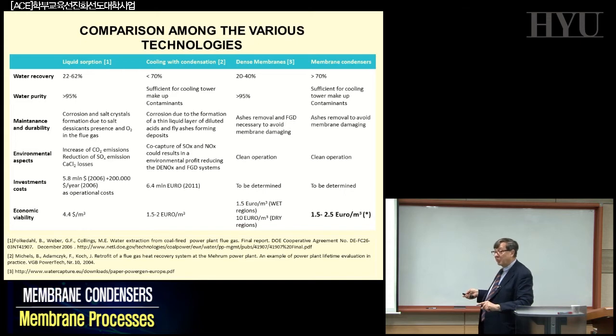When you are working with microporous hydrophobic membranes, and we discussed microfiltration already, the chemistry in the first approximation is not very effective. Here, what is important is the configuration and the morphology of the material. There is a big pore, everything has to go across, there is no chemistry involved, no adsorption, no solubilization, just viscous flow across, or Knudsen flow across. So the chemistry is much less important, and in particular, these materials are perfluoropolymers, which are stable to most of the contaminants, much more stable than the ones we are using here. So that's why this kind of methodology is becoming more and more of interest in our personal opinion.